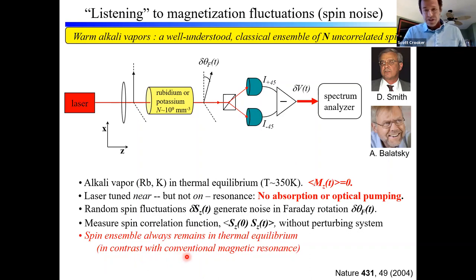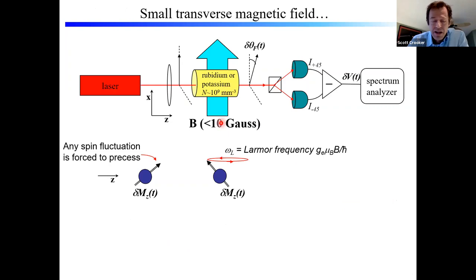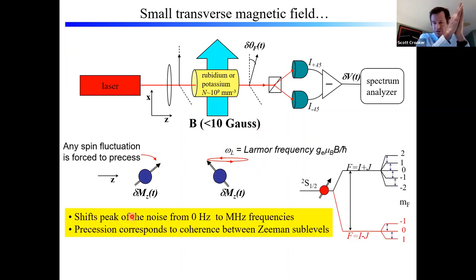And this is very much in contrast to conventional methods for magnetic resonance. Oh, one small caveat. In many of these experiments, we found it helpful to apply a small transverse magnetic field, just a few gauss. And the reason for doing that was so that any fluctuations along the Z direction would have been forced to precess about this magnetic field. And technically, what that did is just shift the peak of the noise from zero frequency up to megahertz frequencies where things are generally quieter in the lab. And what that corresponds to is spontaneous coherences between Zeeman sublevels in the magnetic ground state of these atoms.